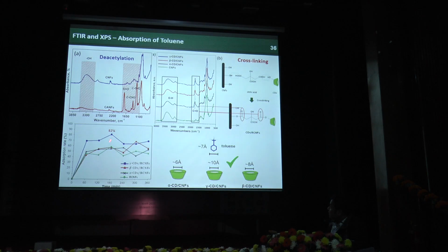So you can see after modification, the absorption property. Most of the industry use toluene as a solvent for their process. So in the wastewater, you can find too much toluene content. So in order to remove the toluene, we use our absorbent nanofiber material. It is very easily handleable. Once it is absorbed, you don't need to go for a purification or separation process. You can just remove it from the wastewater. So we achieved close to 80%, which is also very high.